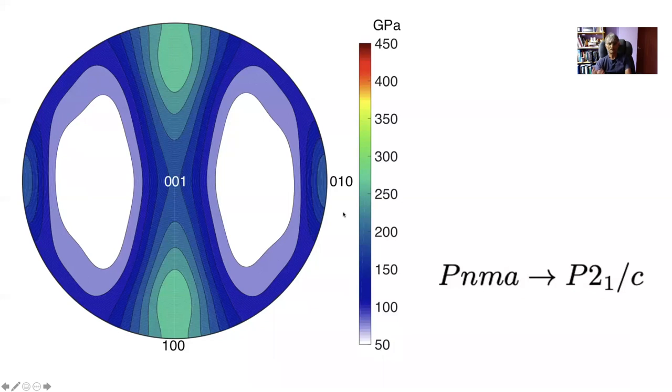And the elastic constant C44 is particularly small in cementite. And sometimes, you know, when we do first principles calculations and we do them a little bit sloppily, we get a negative value for C44, which doesn't make sense because the lattice would be mechanically unstable. So, but if you do them rigorously, you get a finite value for C44.